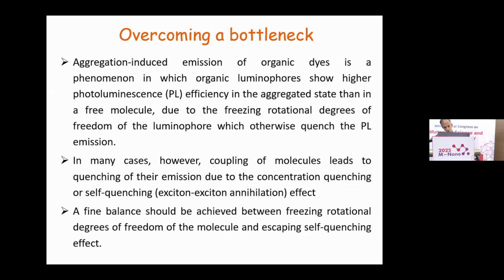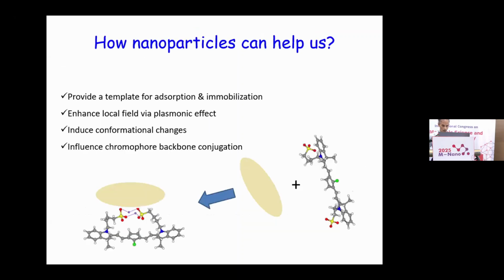When we talk about aggregation of molecules, which leads to higher quantum yield of the emission, we also should take into account that aggregation usually results in quenching of photoluminescence because of exciton-exciton annihilation of the neighboring molecules. So we need to find a specific balance between aggregation and enhancement of emission. So we can use nanoparticles, which can help us to enhance photoluminescence. And this enhancement can be realized in different ways. For example, nanoparticles can provide a template for adsorption and immobilization, when vibrational modes become suppressed.